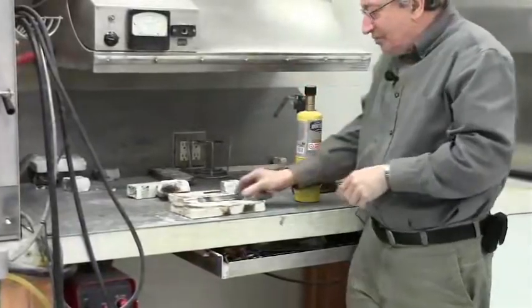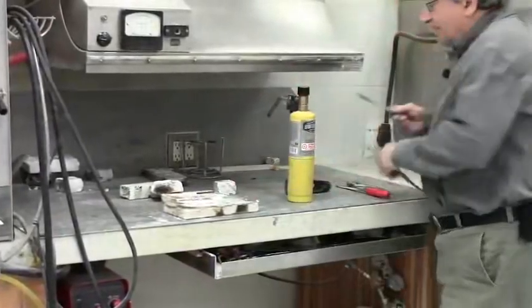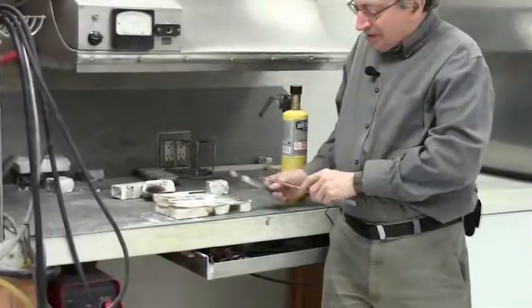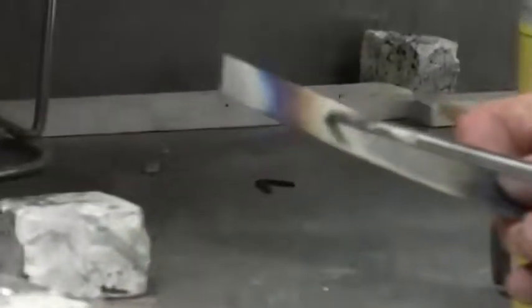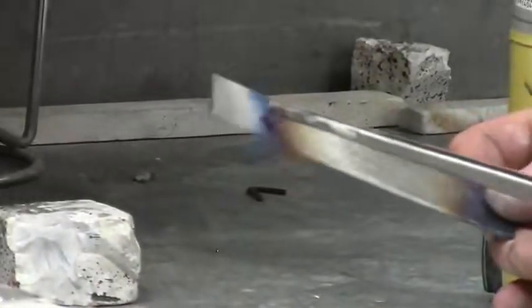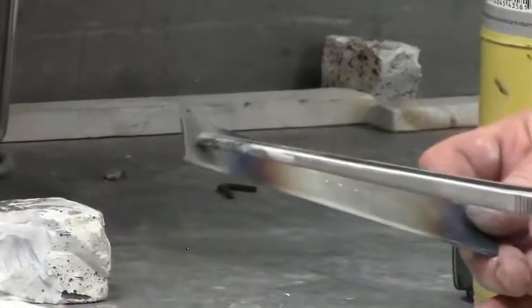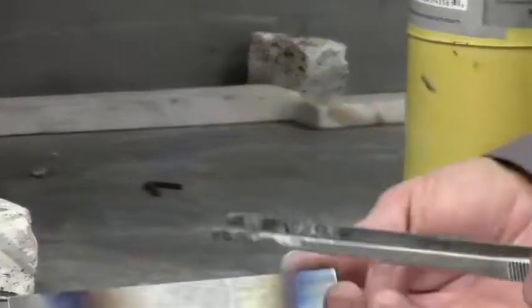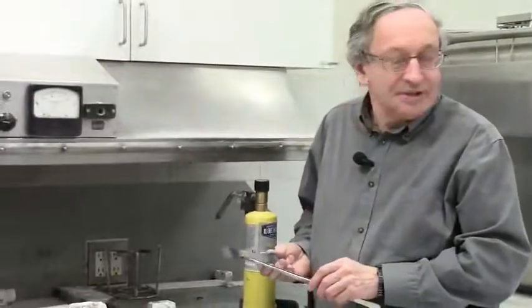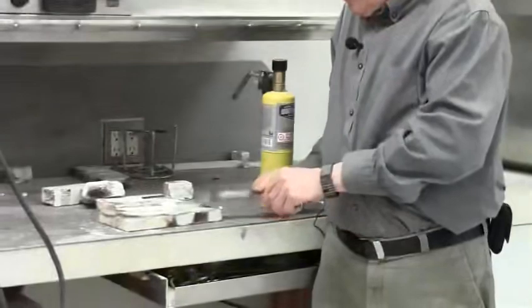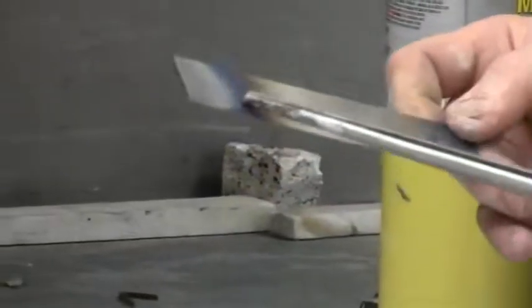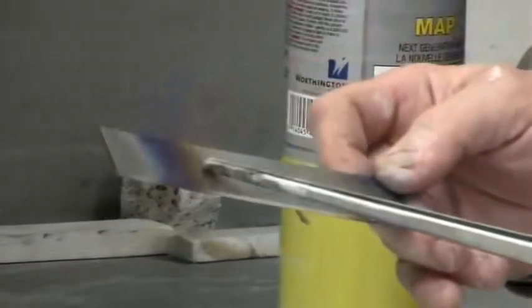If I look at this piece and I look at the color gradation, I can see straw, dark blue, light blue, and this was overheated already. It went gray, so that's overheated. So the tempering range is straw to dark blue. Dark blue is Rockwell, say 56, 55, Rockwell C. Straw is Rockwell C 60.